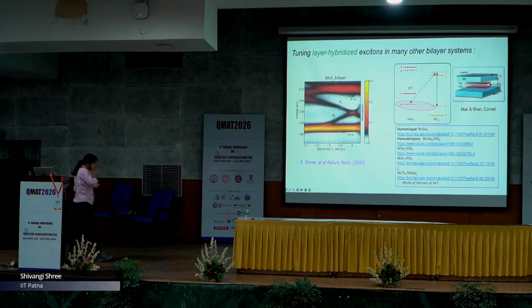And the interlayer exciton that we see in 2H homobilayer, then I made another sample with a gated device to see really the characteristic feature, the Stark shift, and here we have it at 0 field. So, this is a reflectivity measurement plotted as a function of field. Here we have the A exciton, the B exciton, intralayer, then we have the interlayer exciton which is degenerate at 0 electric